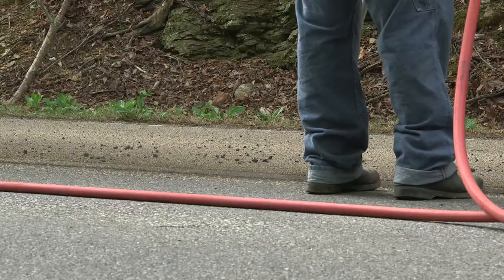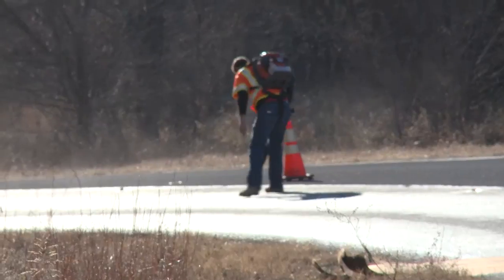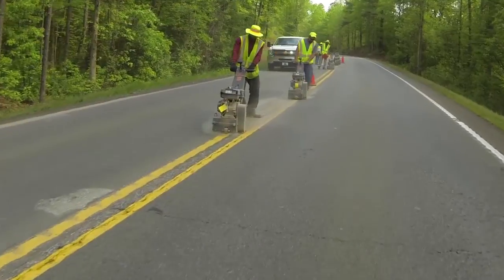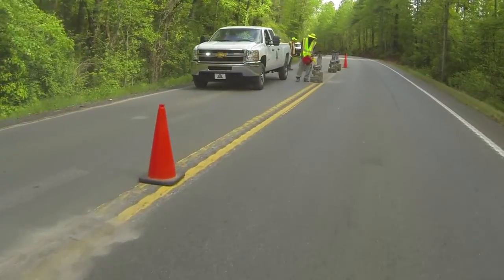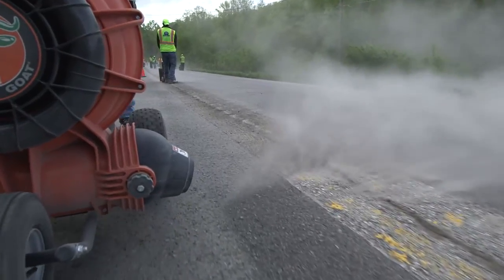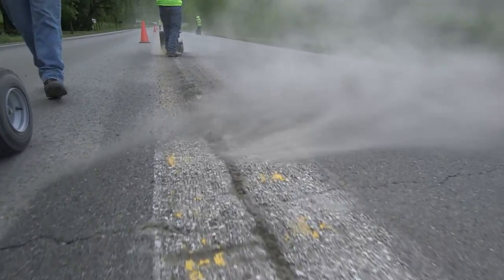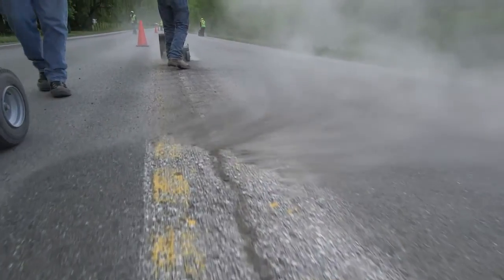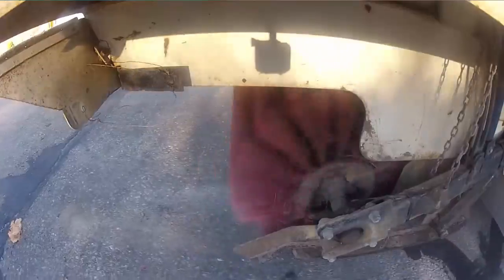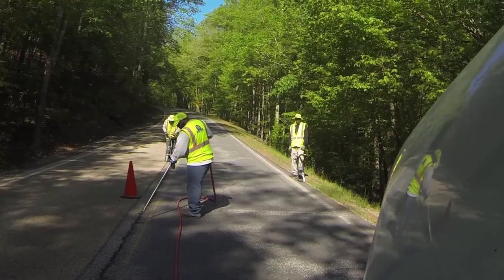Surface preparation begins with cleaning the pavement surface to remove oils, grease, and other matter. Thermoplastic pavement markings within installation sections need to be ground off the surface, or the HFST will not properly adhere. While there are many techniques for cleaning asphalt pavement surfaces, it is important to remember that insufficient cleaning and drying may result in delamination of the binder from the pavement surface. Asphalt pavement surfaces may be prepared using a mechanical sweeper and high-pressure air wash.